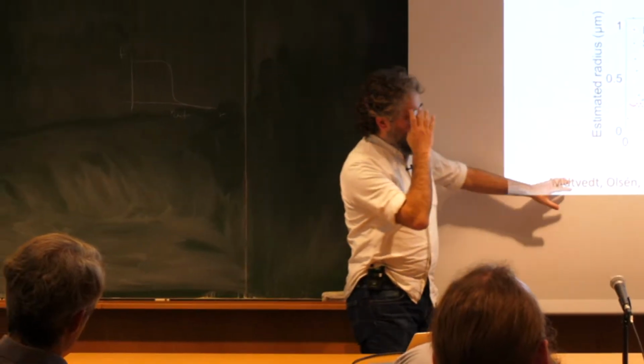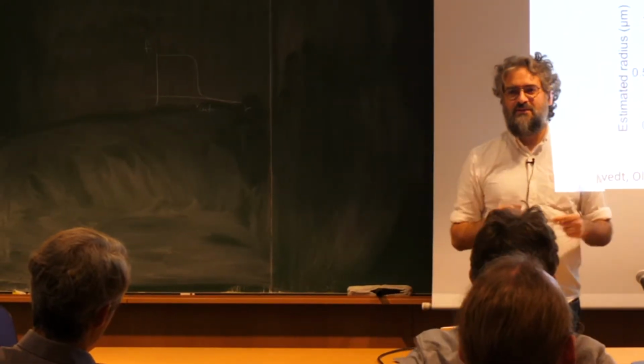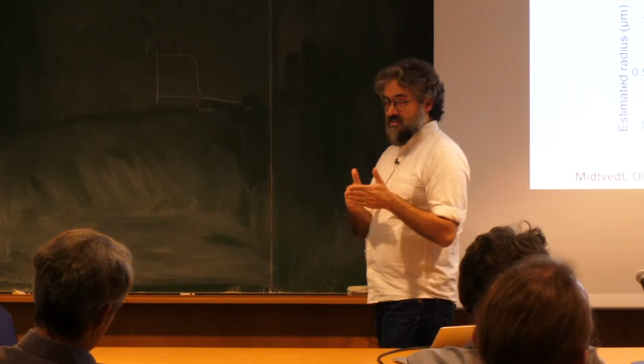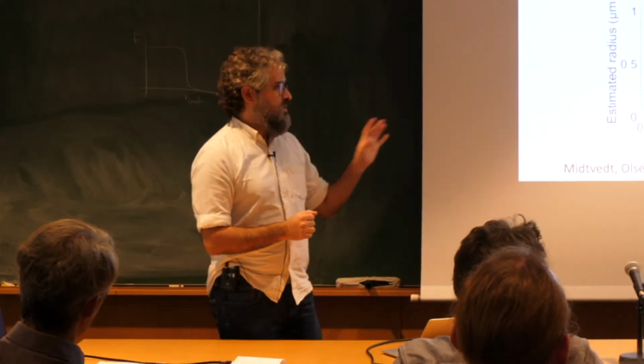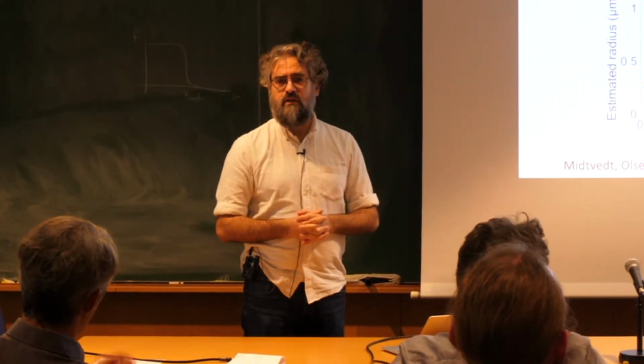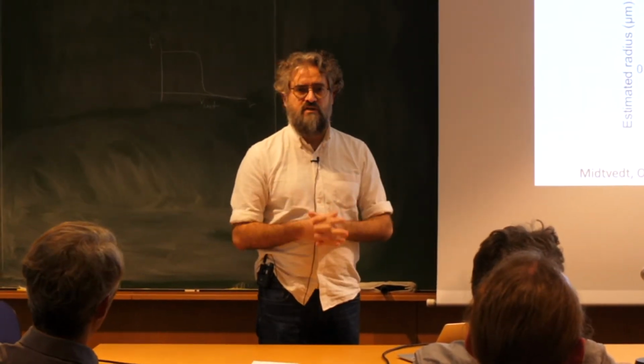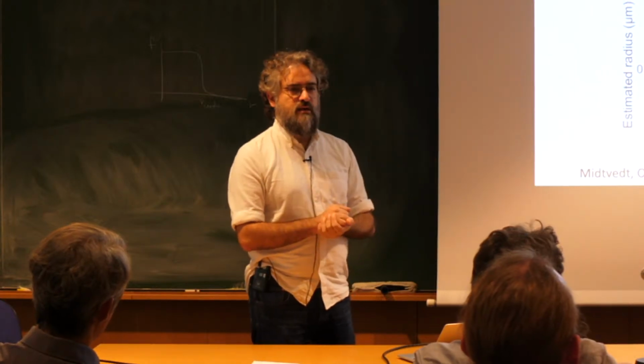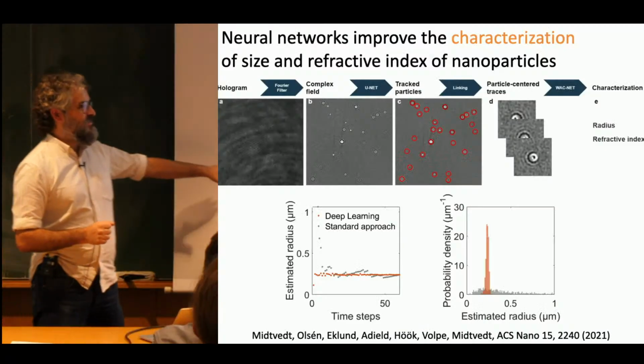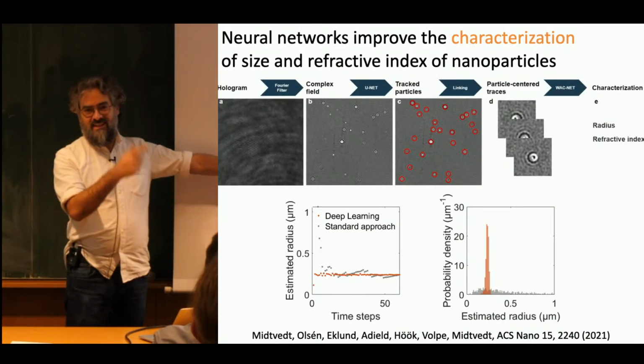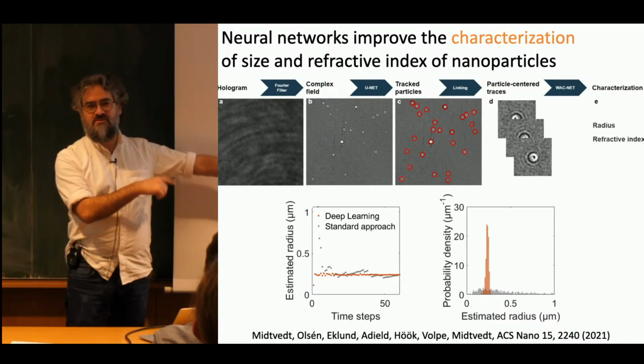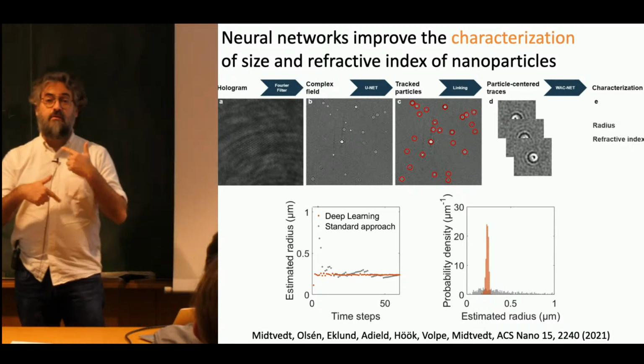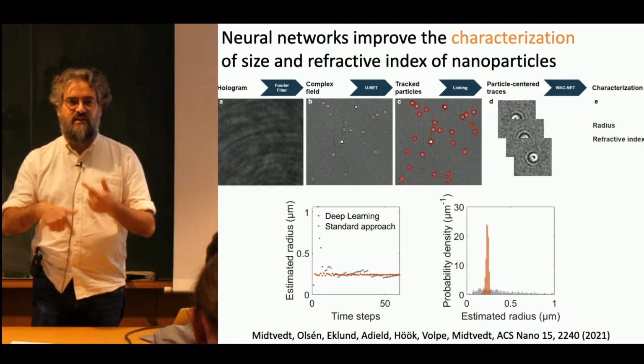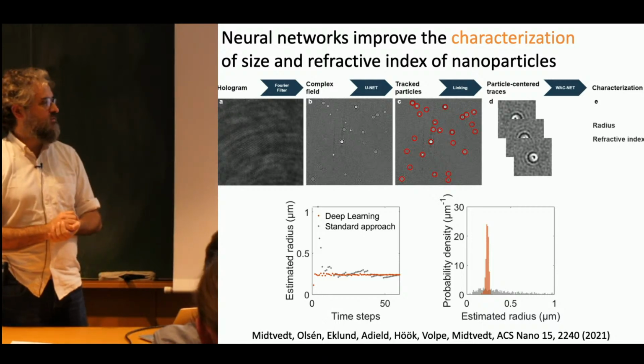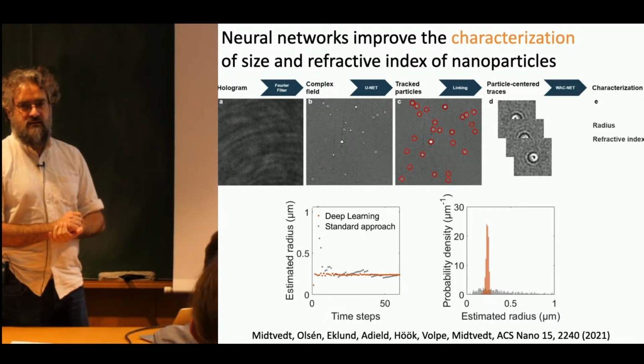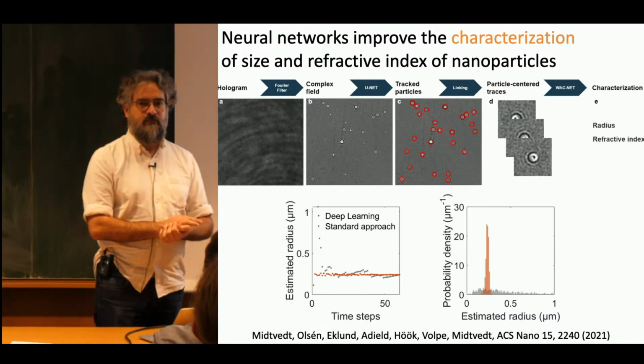The interesting thing maybe in this network, since we are going into details, is that here we use a sequence of images and we use some concept that is connected to attention. Maybe you have heard of transformers and so on. So we basically, without actually knowing, use essentially attention and not self-attention, to be fair, but we use attention to decide which frames are the most significant for the network to analyze. So that's actually the trick that made the huge difference in the result.